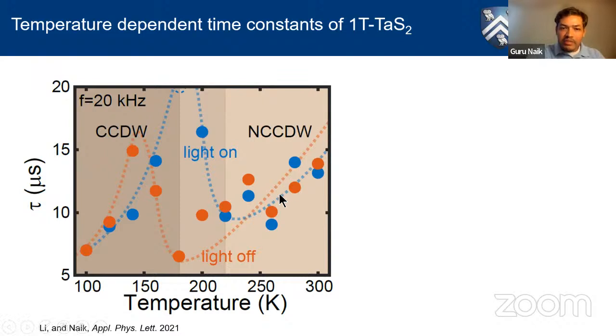So as we reduce temperature, the time constants decrease. So they become faster and faster. But as we approach this phase transition point, which is about 180 Kelvin, where the Mott gap shows up, we see that the time constants go up again. They shoot up to a very high number, and they again drop as we reduce the temperature further. So this was quite interesting. We didn't really know how to explain this phenomenon.